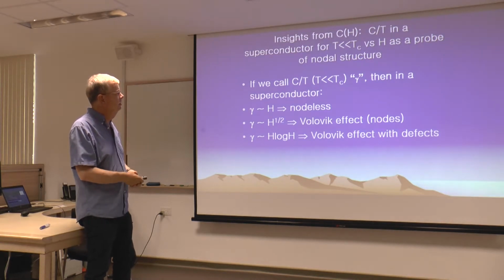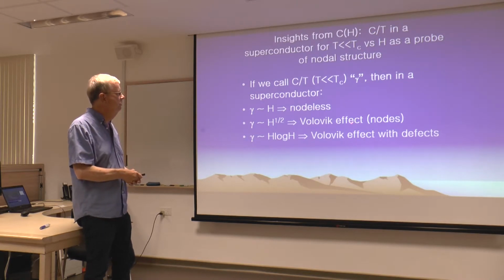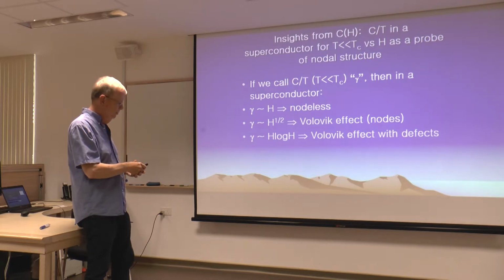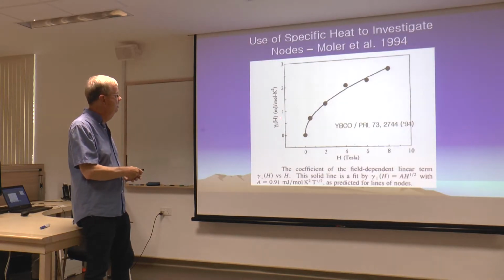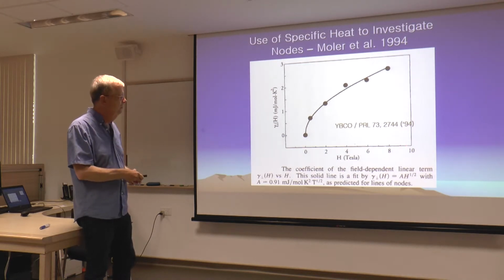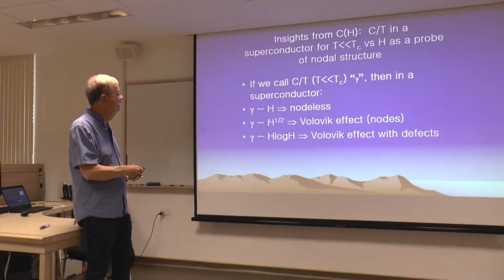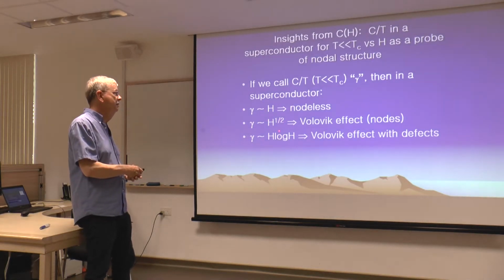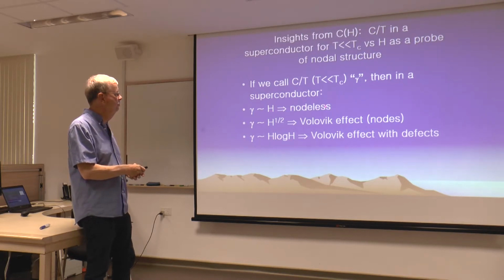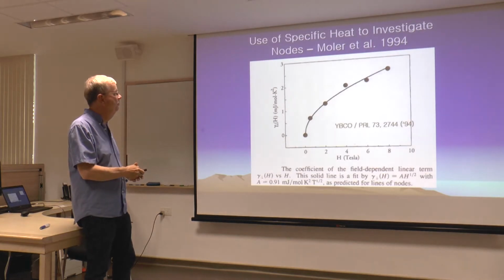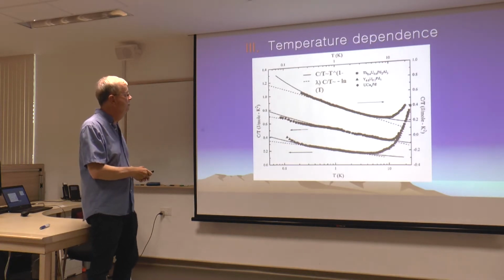So we talked a few times about how to determine nodes, and we said that Volovik had a theory that said if you measured the specific heat, like Moler did, in the superconducting state as a function of field, it went as the square root of H. What I didn't tell you is if you throw in defects, you can wash this out so that it looks like H times the log of H. And of course, if it's just linear, it's just a normal BCS nodeless superconductor. But what I wanted to spend a second on was,